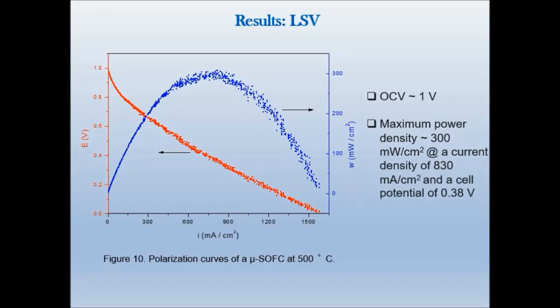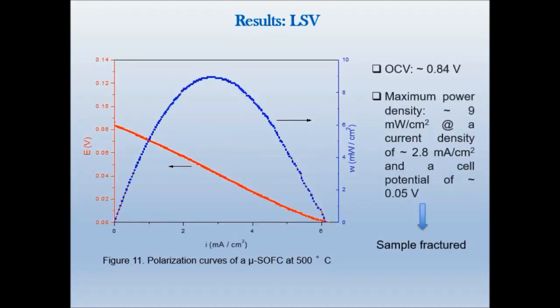About 1 hour later, the open circuit voltage had decreased. Linear sweep voltammetry measurements were performed again. The values of all of the mentioned parameters shown in the previous slide significantly decreased. For instance, the open circuit voltage was 0.84 volts and the maximum power density was about 30 times smaller, giving a value of 9 milliwatts per square centimeter. The cause was that the sample fractured and hydrogen mixed directly with oxygen, and indeed, after cooling the furnace down and taking the prototype out of it, it showed a visible cross-sectional fracture.